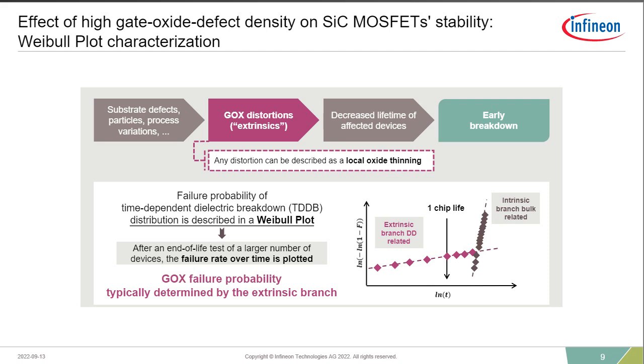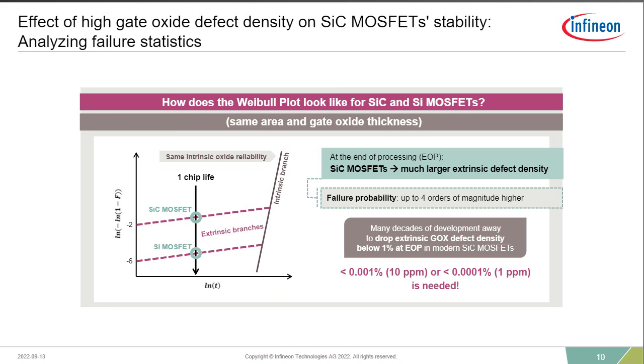And what I'd like to show you as we progress through the slide is the challenges that silicon carbide brings in terms of these extrinsic defects. On slide 7, previously, we had shown you all those little defects, porous gate oxide structure or particle inclusions that happen. And there's a key differentiation between silicon carbide and silicon. Silicon has been in the industry for 30 years, and there's a substantial difference in terms of the ppm rate or quality of the boule or base material that you have with silicon versus silicon carbide. There's almost a 4x order of magnitude less inclusion rate in silicon MOSFET or silicon material versus silicon carbide.